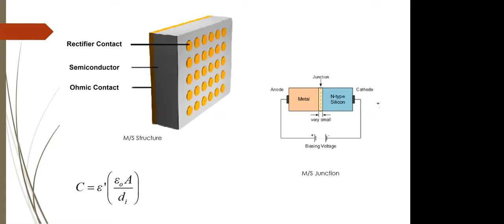with the increase of the dielectric constant of the material and the diode area. But given that there is a limit to increasing the diode area, it's clear that the energy storage capacity of a capacitor depends on the dielectric properties of the material. This situation shows us the importance of studying the dielectric properties of MS structures. For these reasons, in this study, the negative dielectric properties of rhenium N-type gallium arsenide metal semiconductor contact were investigated using complex permittivity, real epsilon prime and imaginary epsilon double prime components. The characteristics of the complex permittivity are obtained using capacitance and conductance measurements at room temperature at 1 megahertz frequency, and the voltage range is -7 volt to 6.5 volt.